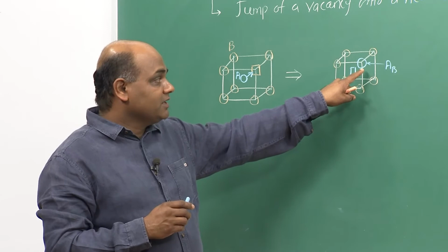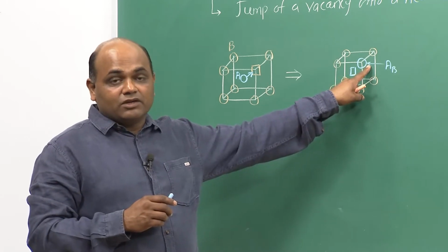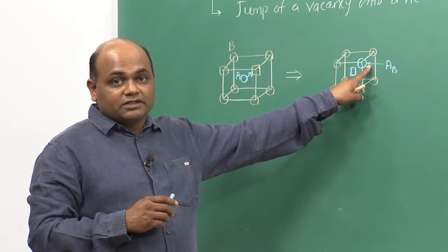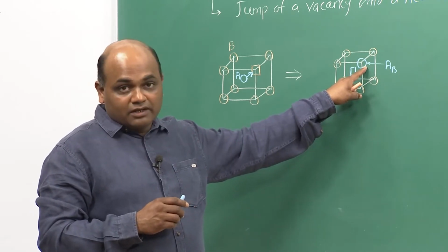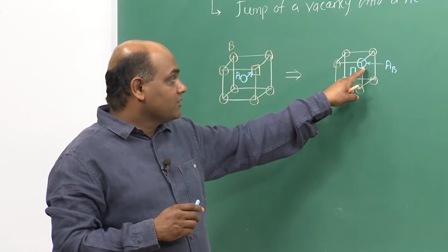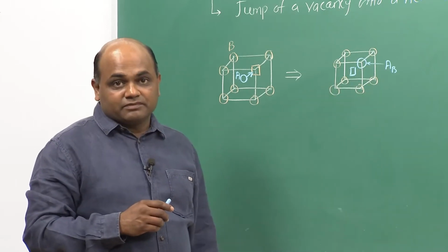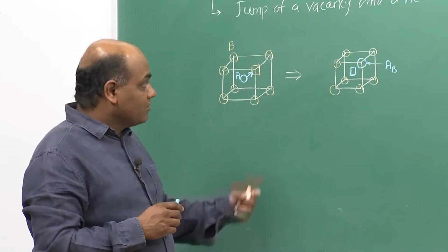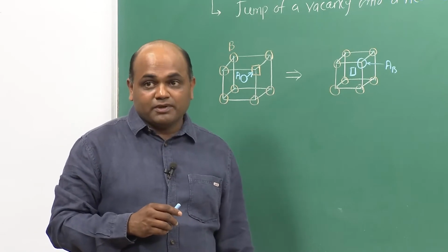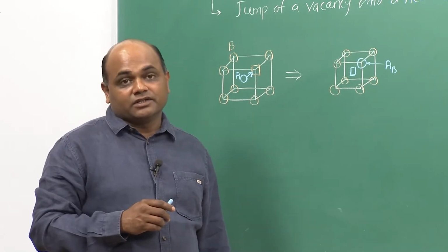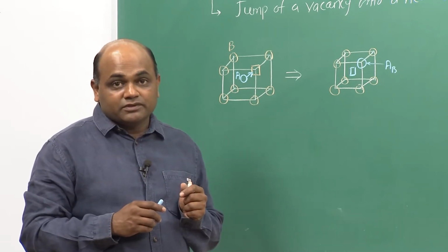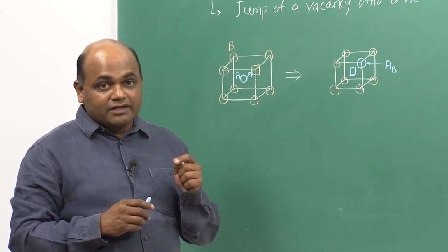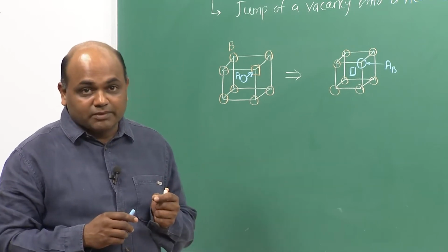For example, in nickel aluminide, especially on the nickel rich side, the nickel anti site equilibrium concentration is considerable, and so the nickel can diffuse by nearest neighbor jumps. Not for aluminum, because aluminum anti site is a high energy structure. So, how does aluminum diffuse? It can diffuse by jump to a next nearest neighbor site.